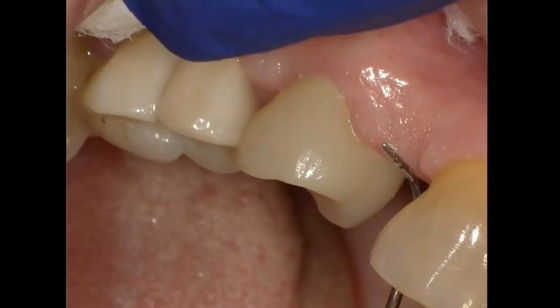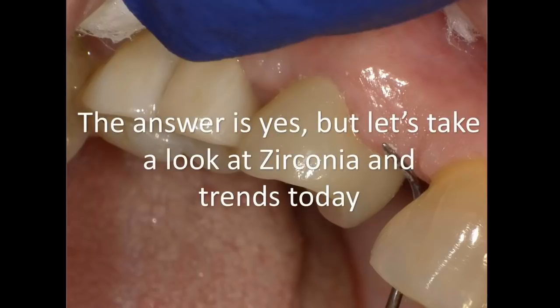And if you can peel away cement and lose that stress of leaving resin cement in the sulcus, that's the key. And you see no bleeding, because this can be done atraumatically. And you don't want bleeding because that can create instant micro leakage. We'll get more into it, but I just want to show you how simple this process can possibly be.